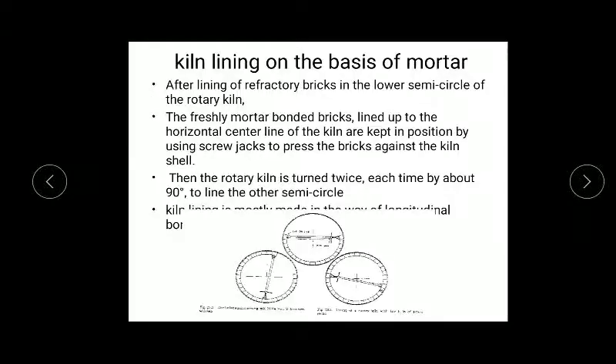So in brick lining with mortar, mortar is nothing but refractory high temperature cement. Say you take that cement, you take refractory brick and you line half a semicircle first of the rotary kiln. Then you place a screw jack which will hold this refractory only at the ends, and when the cement sets, they will all stick to the surface.